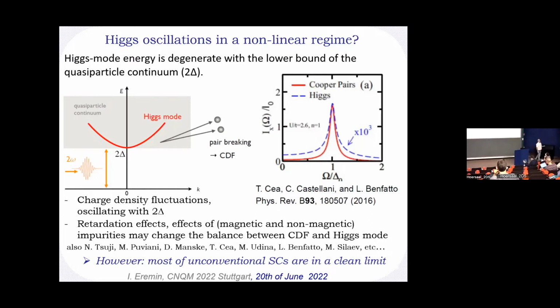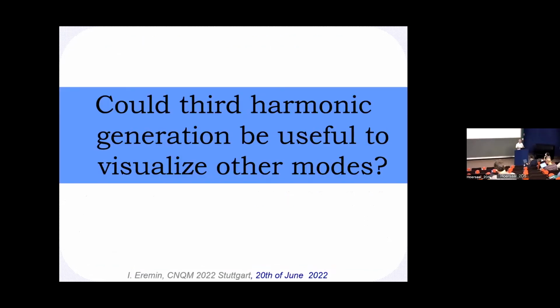the problem comes in unconventional superconductors, because we know these should mostly be in the clean limit. That basically tells you that everything you should see in pump probe type experiments is just a signature of Bogoliubov quasi-particles, which is also oscillating at 2 delta. But now I'm going to argue whether you can actually use this third harmonic to see something more in pump probe type experiments.